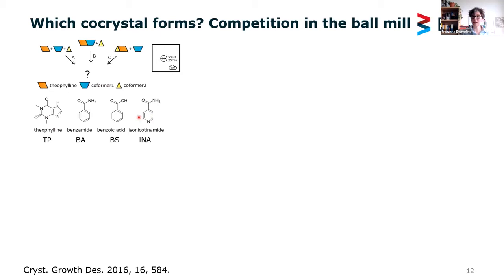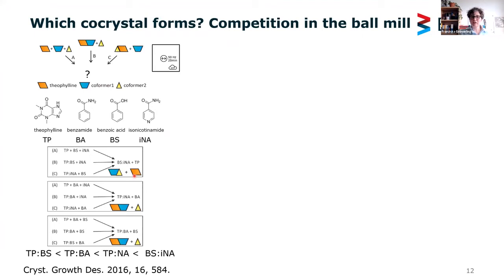And basically, we performed two types of reaction. The first question was, in the presence of two co-formers, which API co-former pair will be formed more easily? And also the second question was then, once a co-crystal is formed and we challenge this co-crystal with another co-former, will we have a change in our product? And here, I won't show data, I just show the outcome of this experiment. You can see that if at any point we have benzoic acid and isonicotinamide together, then they would form a co-crystal and they won't care about theophylline. In the other cases, we could see that the co-crystal formed between theophylline and isonicotinamide is the more stable one, and that is preferred as compared to the two other possibilities.